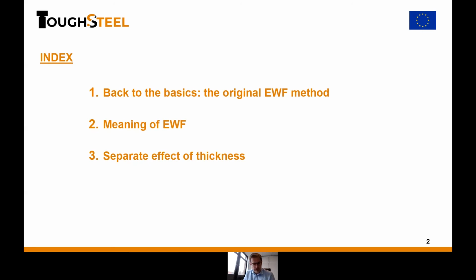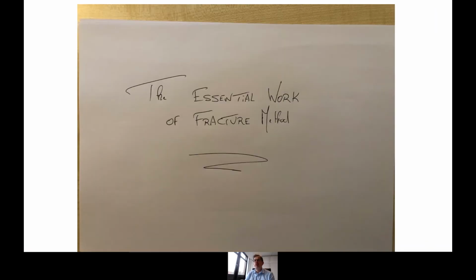And then I will come to one of my preferred topics, which is the effect of thickness on the value of the fracture resistance of thin sheets that you measure with the essential work of fracture or with another J1C or other approach. Understanding this effect better reveals the physics of fracture in thin sheets and gives additional insight on the meaning of the essential work of fracture. So I prepared a very fancy coverage of what is the essential work of fracture.